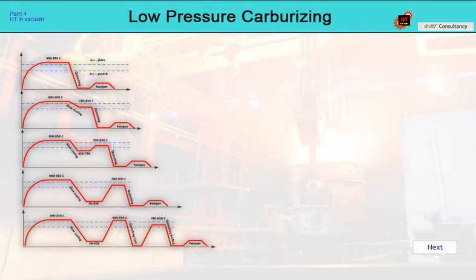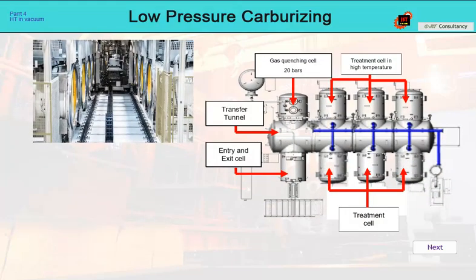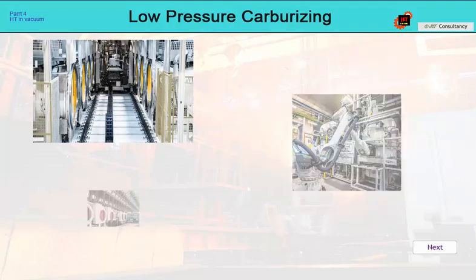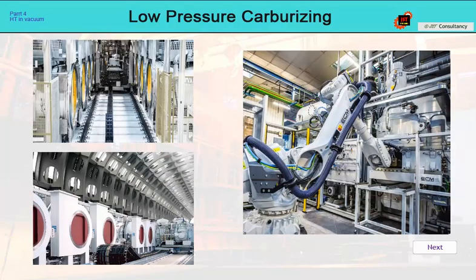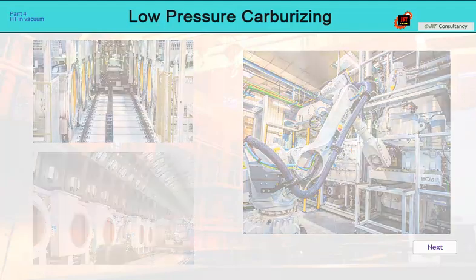A great advantage in choosing the quenching method is provided by multi-chamber systems such as ECM Flex, Jumbo or Nano, or ALD Modultherm. Here we will take advantage of the fact that we have multiple working chambers and each of them can be at a different temperature. We only transfer the load from one chamber to another and then quench it. At the same time, the parts are still inside the vacuum system. In this type of equipment, it is possible to model all methods of quenching after carburizing quite easily and with almost unlimited temperature options for a given operation.